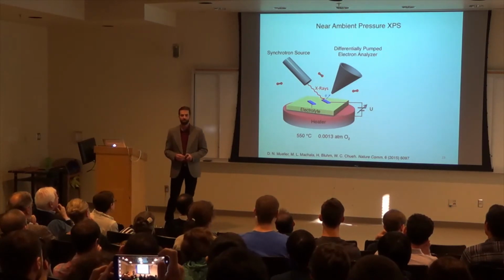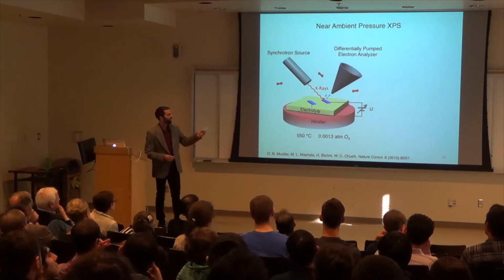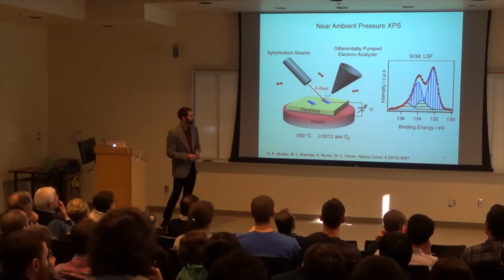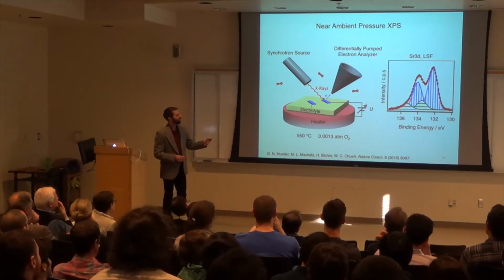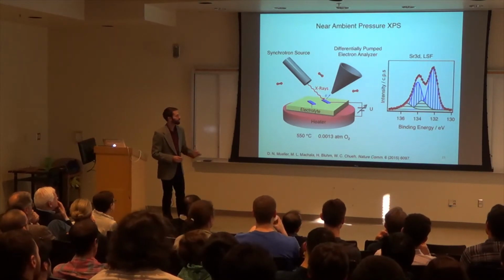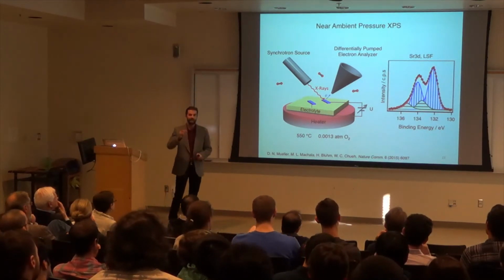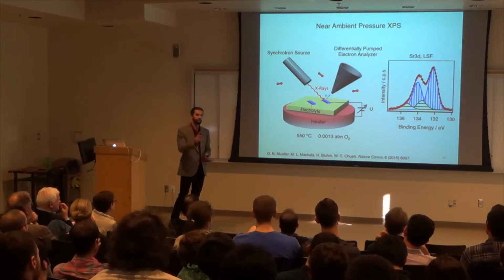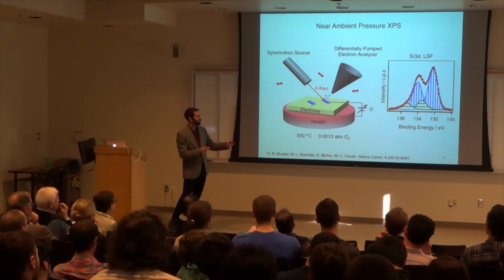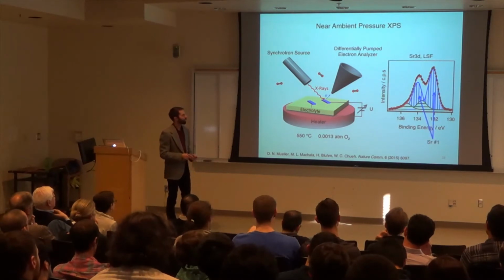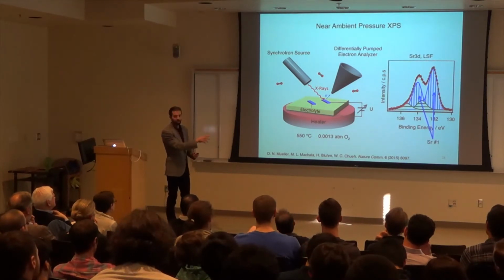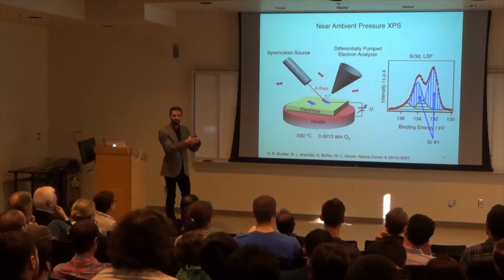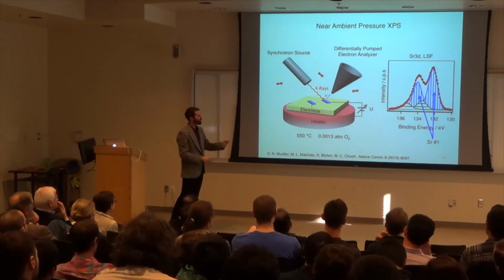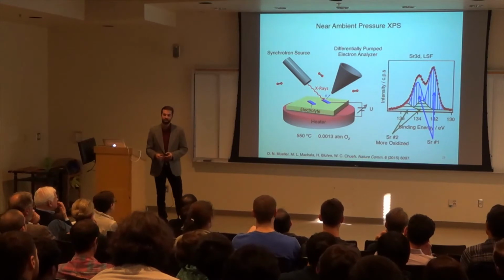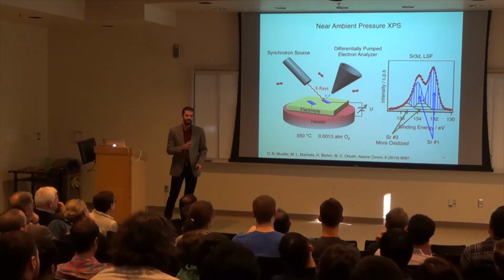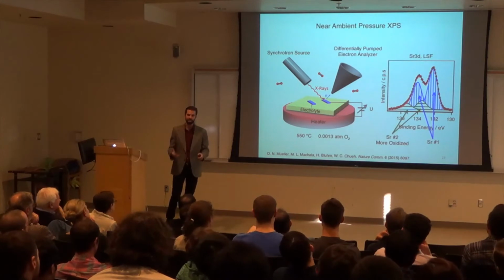And so what I'm going to talk about is what is called X-ray photoelectron spectroscopy, XPS. And what one of those spectra looks like, say for the strontium, for example, is shown here. We have the intensity of the signal in counts per second as a function of the binding energy. Now, one chemical species typically gives a doublet, so two peaks right here. So, to summarize, one type of chemical environment that the strontium atom is in gives one set of doublets. Another one gives a second set of doublets. And the higher binding energy means that this particular species is in a highly oxidizing environment.